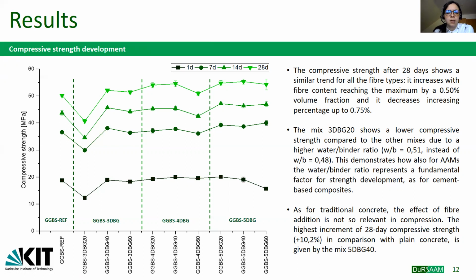In fact, a higher water binder ratio corresponds to a lower compressive strength. However, as for traditional concrete, the addition of fiber does not really affect the compressive strength. As we can see, the compressive strength value of fiber reinforced concrete compared to the plain concrete, the first on the left, is not so different.